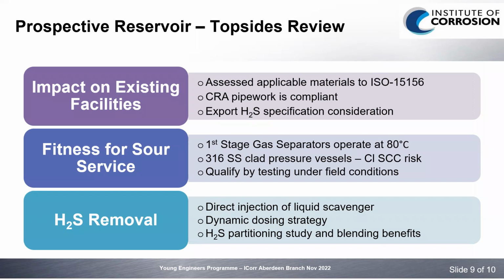What we suggest doing is qualifying the material under field conditions to Annex B of Part 3 of ISO 15156. If this were not to be successful, we would recommend chloride inhibitor being injected upstream of the separators, and as a worst case scenario, recladding the inside of the vessel in contact with the liquid phase up to the high liquid level in the separators.